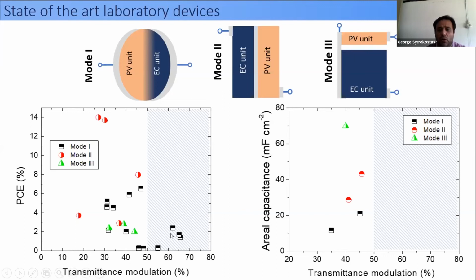Moreover, as I said previously, we also care about the charge storage properties of these devices. Indeed, in recent years, we have reports where the areal capacitance of these devices has also been measured. In the right graph, we see the areal capacitance of these devices with respect to their optical modulation. We see that we have significant values of areal capacitance, but still the optical modulation is not above 50%. So if someone wants to improve the optical modulation, but keep the areal capacitance at a reasonable level, they can take ideas from a field that is very close to photoelectrochromic windows, that is the electrochromic energy storable devices, where in this case we have devices with optical modulation above 50%.